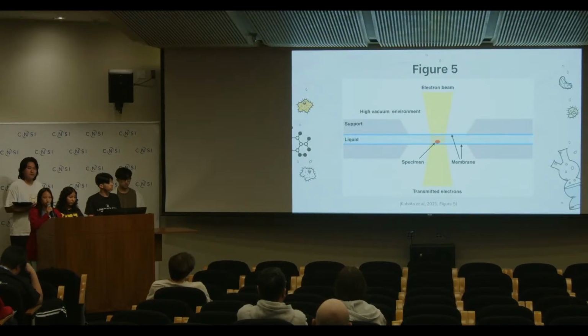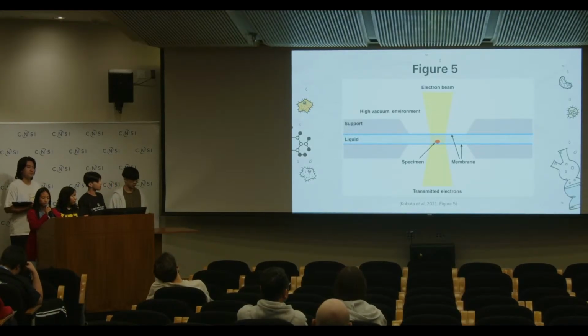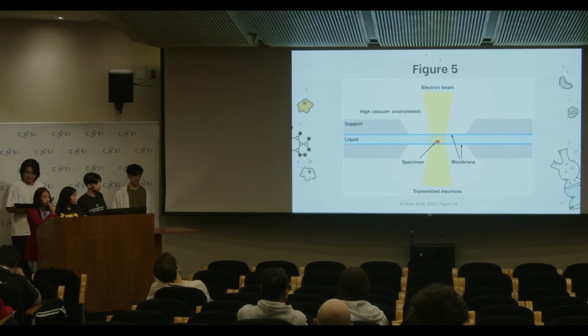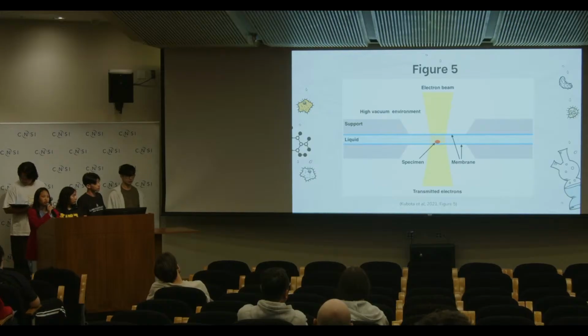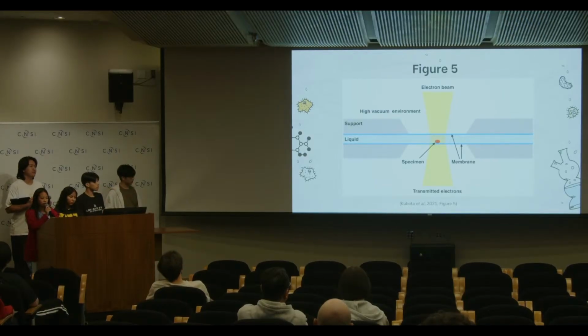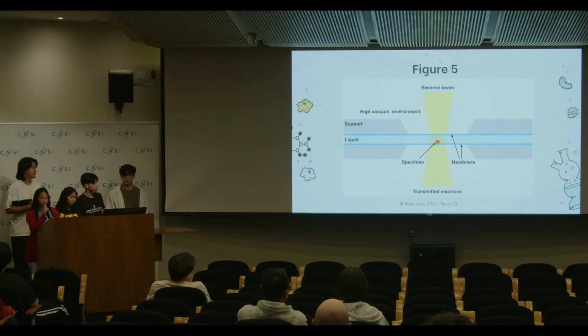In Figure 5, you can see that the liquid sample is placed in a small space between two thin, tough, and high transmittance membranes, typically between 20 and 50 nanometers, completely enclosing the liquid cell. The liquid cell is a prepared sample environment that allows the electron beam to pass through for imaging while staying in a liquid state. The figure also shows the need for a thin liquid sample, with the sample staying in a narrow space between the two membranes.